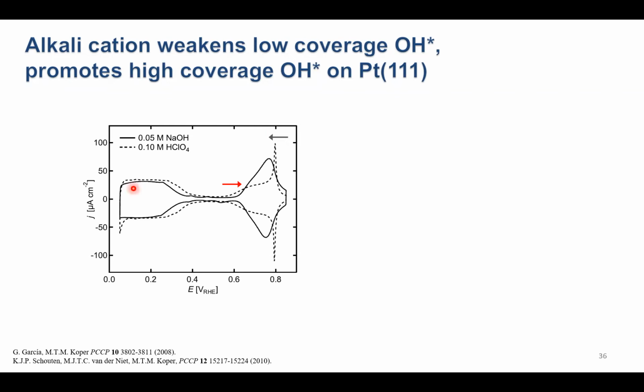So here we're showing CVs measured on platinum-111 in perchloric acid, that's the dashed line, and in sodium hydroxide, that's the solid line. We already knew that this high potential peak corresponds to OH adsorption through lots of work from other people over the years. We can also test this with DFT.